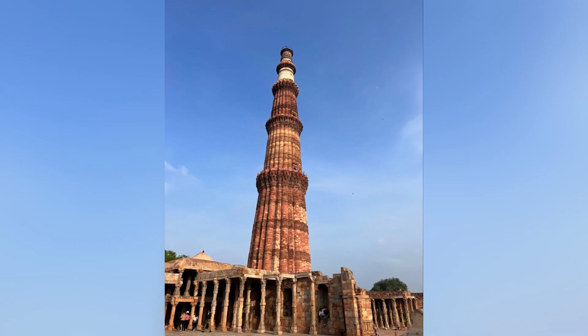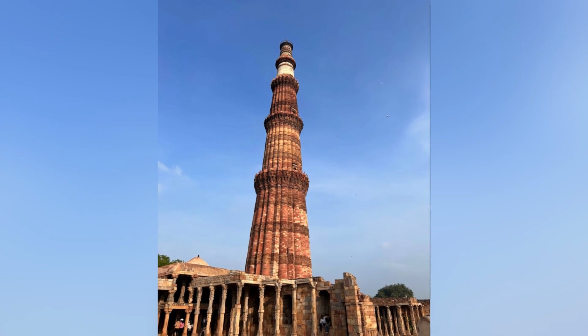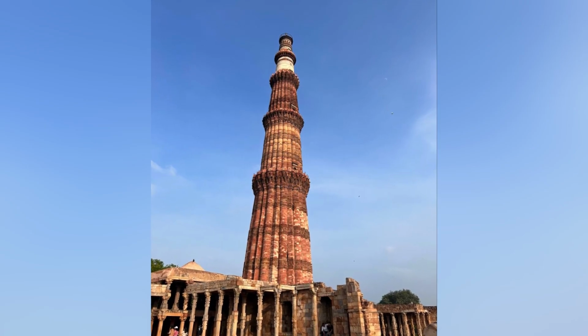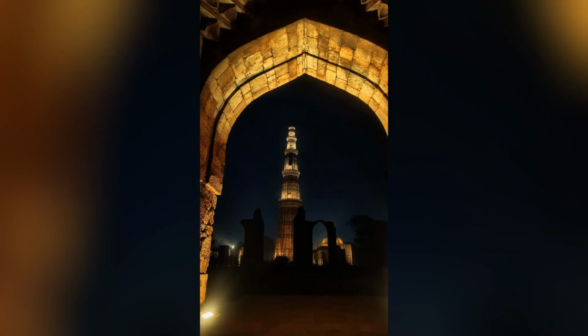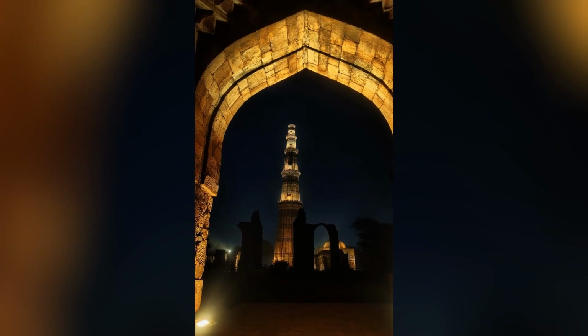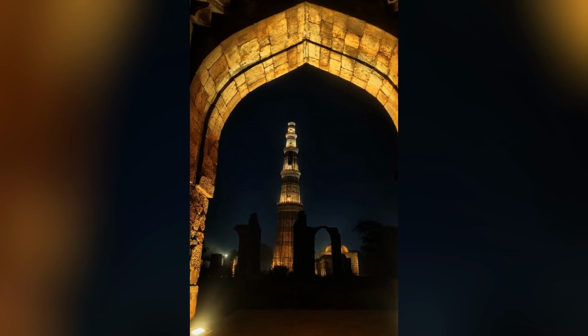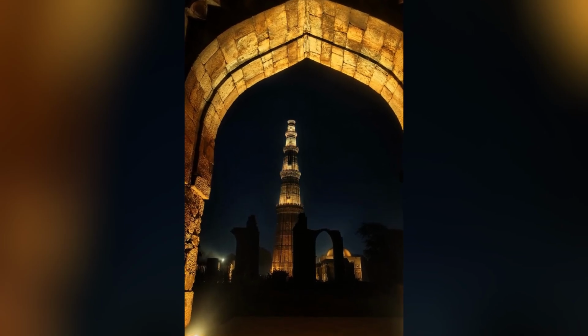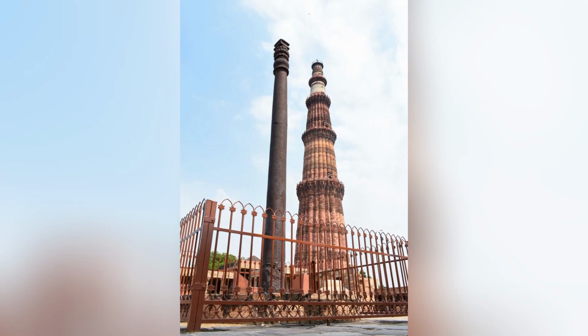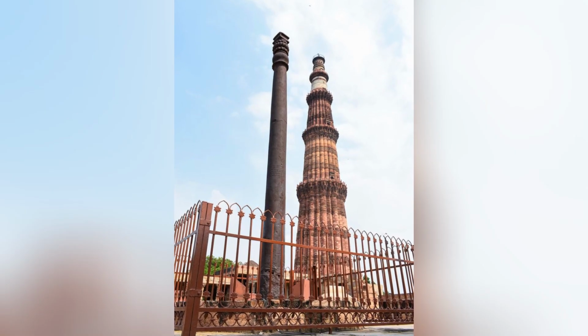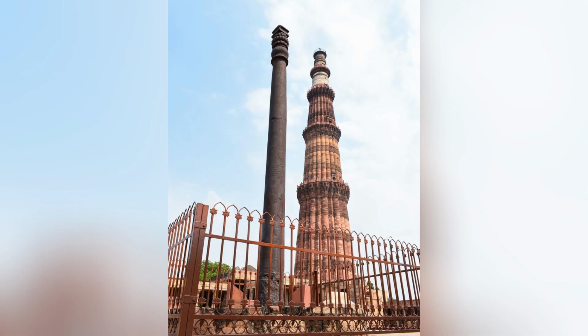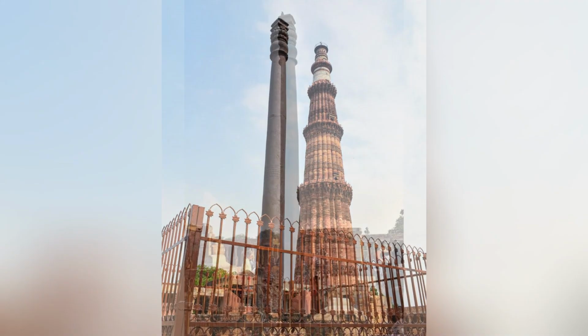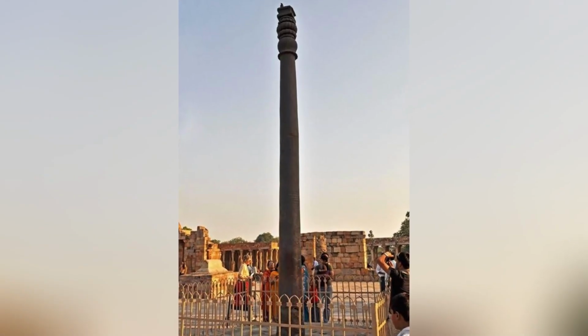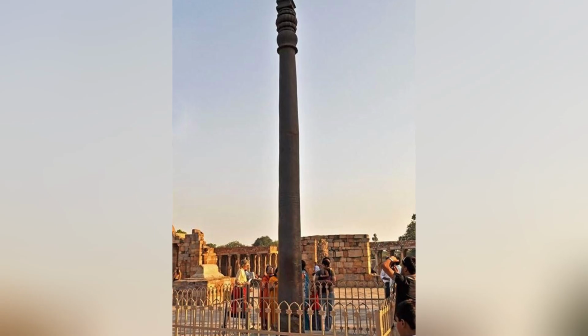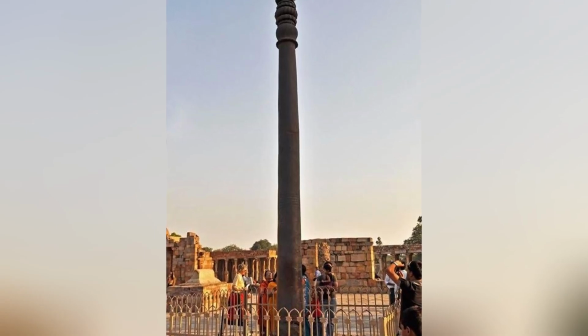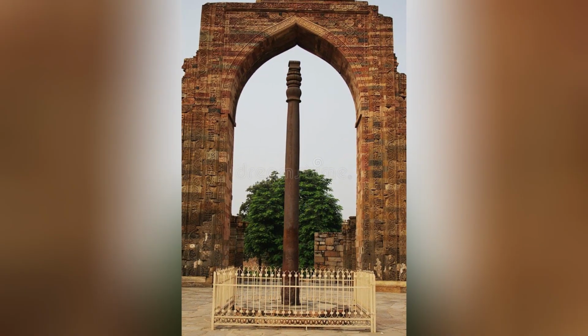The forging process that was used to consolidate the blooms and to shape them into the form of the pillar involved repeated cycles of heating and hammering that served multiple purposes. The hammering expelled the slag that was trapped in the bloom, consolidating the iron into a dense, homogeneous mass. The heating and the hammering also distributed the phosphorus throughout the iron, ensuring the uniform distribution that is essential for the formation of a continuous, uniform protective film. And the repeated heating and cooling cycles that were part of the forging process may have promoted the formation of specific microstructural features that contributed to the pillar's properties.